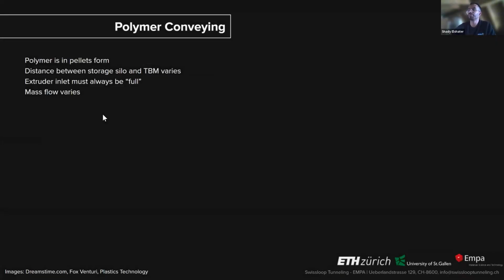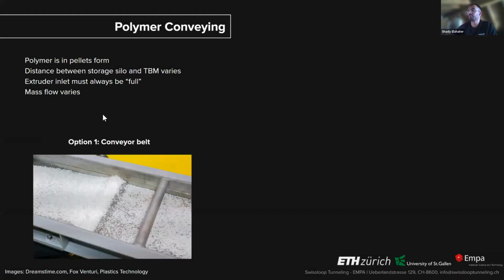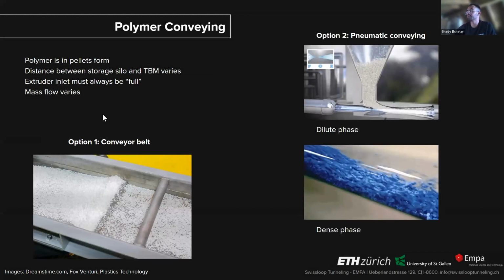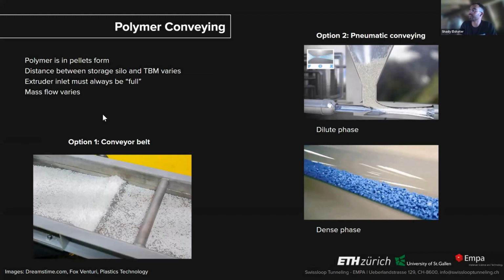For the polymer conveying, this polymer in pellet form, the distance between the storage silo and the tunnel boring machine varies, and the extruder inlet has to be always full, like this hopper. The first option that we looked at was a conveyor belt, which is a simple solution, but it takes up too much space. That's why we looked at pneumatic conveying.